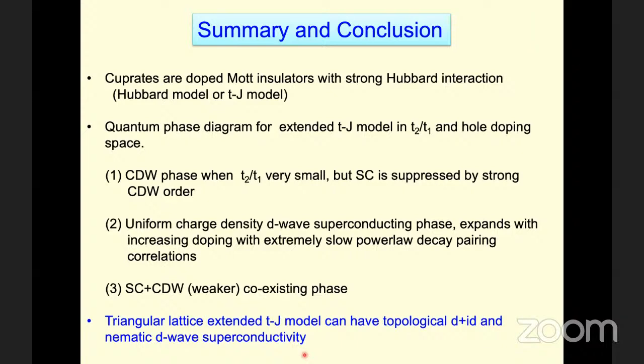Then for the larger T2/T1, or numerically J2/J1, I think the possible magnetic state is the stripe phase. So we find the stripe phase can also have, upon doping, superconductivity emerge. But that case may be more consistent with nematic D-wave superconductivity.